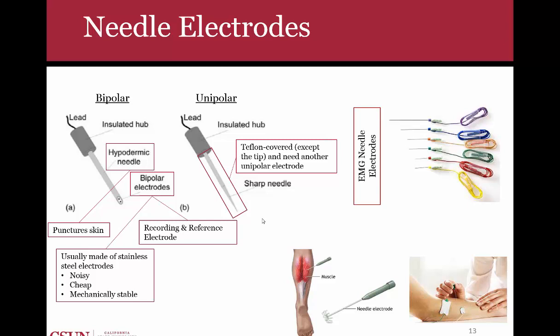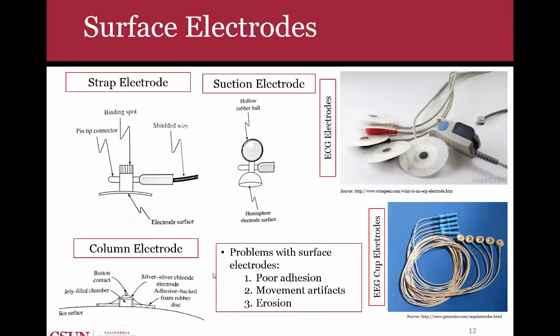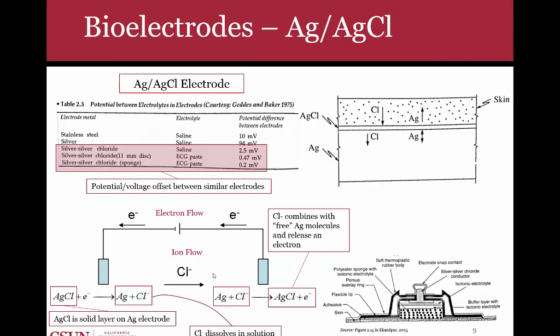In this case, the electrodes are not made of silver chloride. They're actually made of stainless steel, and that's because you have to make them mechanically stable because you are puncturing skin. You don't want the electrodes to break, so that's why they're made that way. They're mechanically stable, they're also cheap, but they're also very noisy. Noisy because if you go back to the previous slide, you get 10 millivolts of potential difference across two stainless steel electrodes. So that's quite a bit, again, in comparison to like say 0.2 or 2.5.